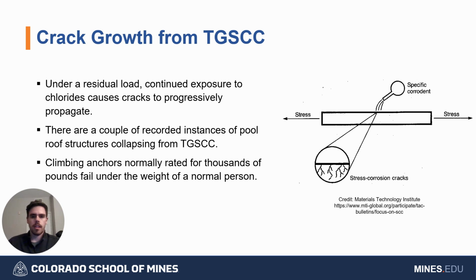So how do cracks actually propagate during TGSCC? Well, when a material like stainless steel is put under a load and chlorides are allowed to continually corrode its microstructure, those corroded regions eventually form crack tips. Those crack tips then start to grow as the corrosion eats away at the steel's molecular bonds, and the applied load further separates the material, which we recognize as further crack growth. Once the cracks have grown sufficiently, the steel will fail.